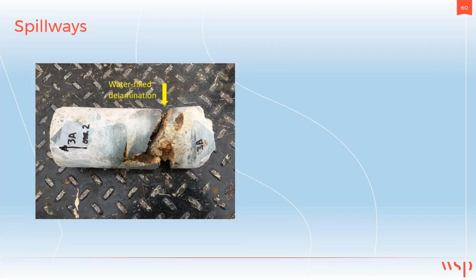Looking at the GPR profile, we got a very strong reflection at a surprisingly shallow depth. The reflections were coming from less than a foot deep, even though we expected them to be at least 3 feet down. Then we took some cores and saw there was a wide water-filled delamination anywhere from 6 to 8 inches deep. So what does this mean for our investigation, and why couldn't we make sense of our GPR data?